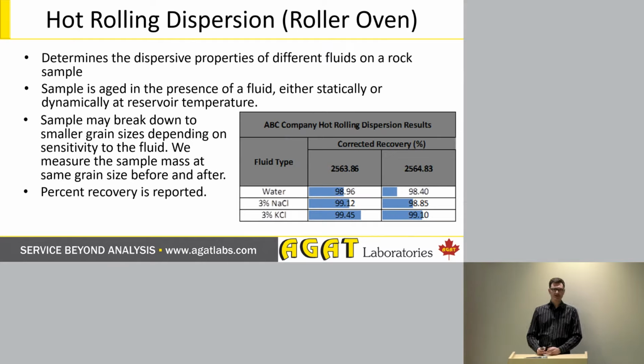The purpose is to roll the sample at a certain rate and for a certain length of time, and then see how much of it was broken down to smaller sizes during this process. So if we see very little breakdown, it means that the fluids that it was mixed with were not precipitating a faster disaggregation of the sample. Whereas if we see a reduction in grain size, it means the fluids used were not particularly effective. In the example here, water was the least effective.